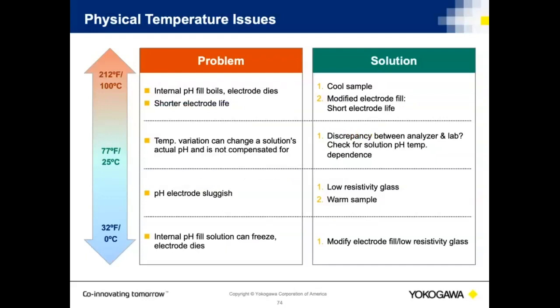Temperature. I already mentioned the issue as far as temperature. We have to watch the temperature. When we remove a probe from a process, my example before was an SCR, the probe is at 180 degrees, it's not going to last as long as it lasts in a high purity application, because in a high purity application, we've already removed most of the heat, in our primary coolers and our secondary coolers. So the issue on the SCR is I have to allow temperature stabilization to occur when I pull a probe out of a process.